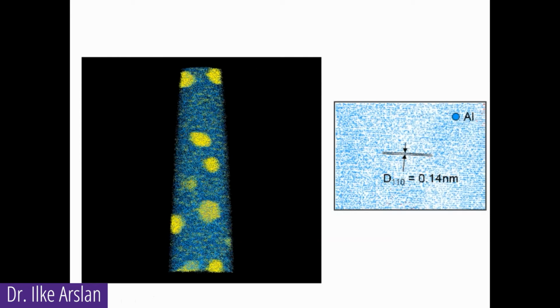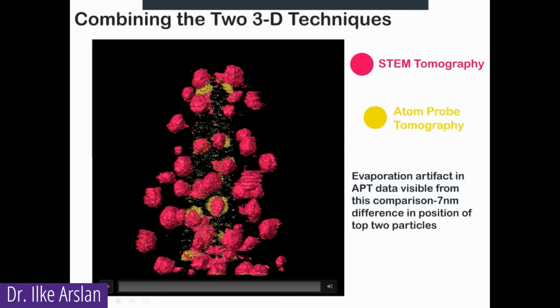Then we took that and put it into the atom probe, and since the Z direction is the highest resolution direction in atom probe, we were able to see those 1.4 angstrom crystalline spacing of the aluminum. And what we did was put these two on top of each other. We superimposed all of the particles so that we could figure out what the artifacts were in both of the techniques. So we can see an evaporation artifact because these two particles should be in here, but they're not. In atom probe tomography data, you can often get artifacts in the evaporation.